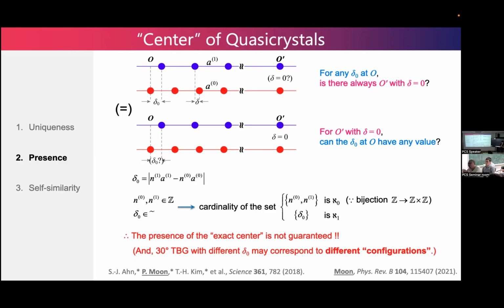If you allow lattice relaxation, is it possible that the system will undergo a very tiny relative shift of the two layers to avoid an exact center, but then the system will be divided into several different domains? Yeah, it is possible. As Koshino mentioned, it avoids AA. Right, you need a way to escape. Not much way to escape because the unit cell is very small. In the low-energy region it can escape, right? It also escapes, but very little, almost not identifiable. That's interesting. Very small.